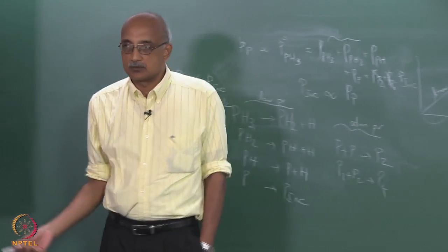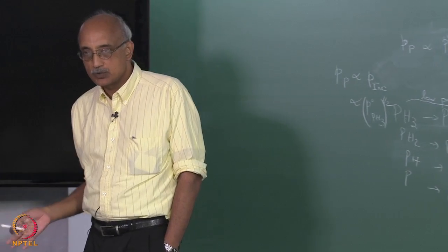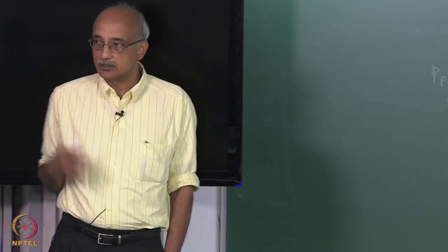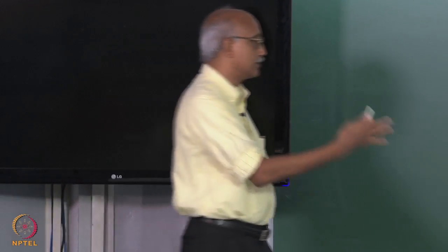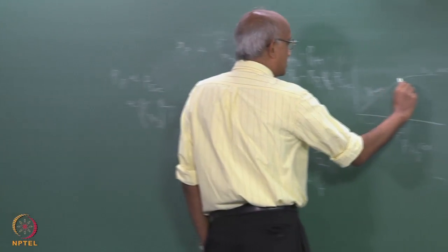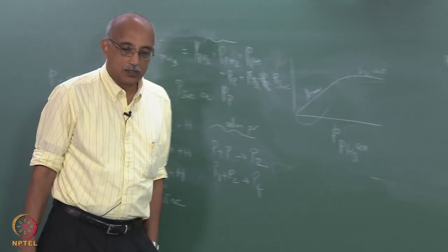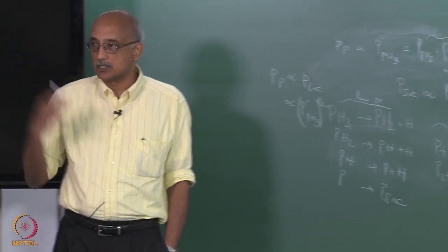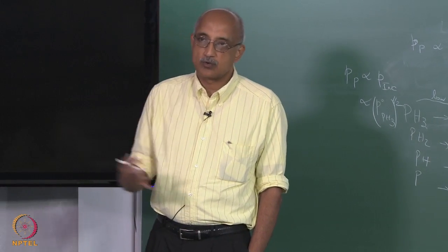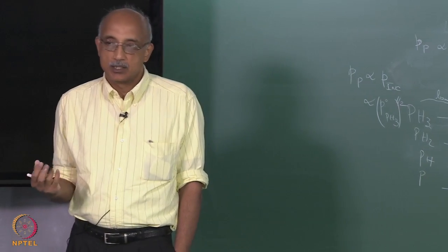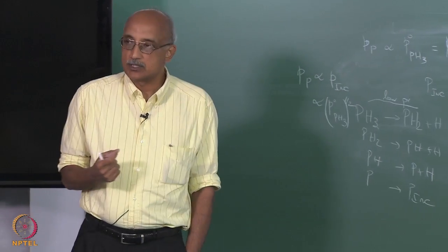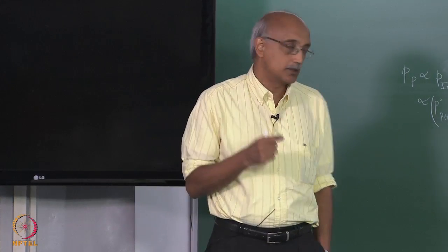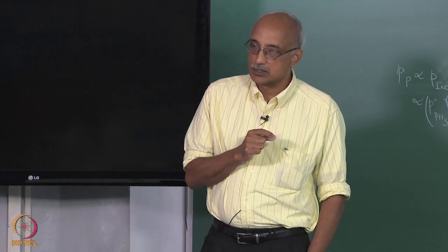The equilibrium has shifted from PH3 and PH2 being the dominant chemical species to P2 being the dominant chemical species. And if you keep increasing the pressure further, you will essentially see a leveling off or asymptotic behavior, because the dependence will become 1/4 and so on. So, the higher order phosphorus molecules that you start forming, the less will be the influence of initial feed pressure or fill pressure of phosphine on the amount of phosphorus that gets